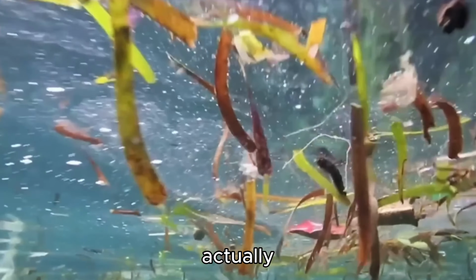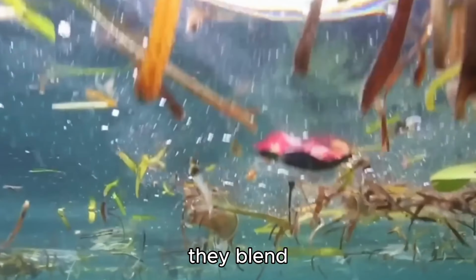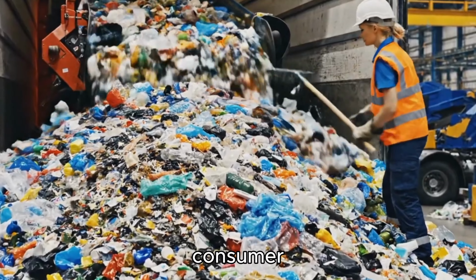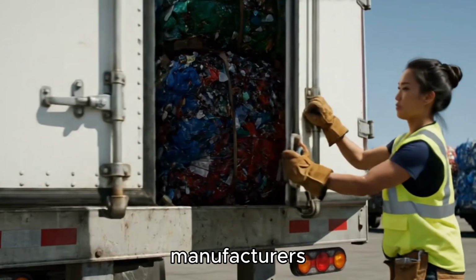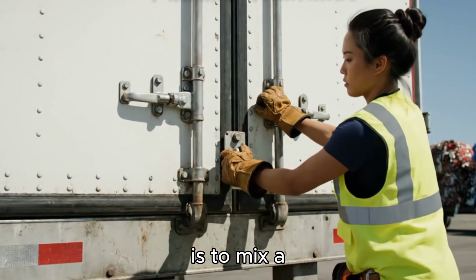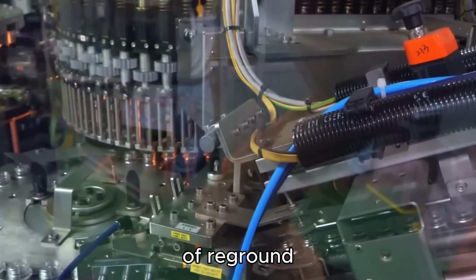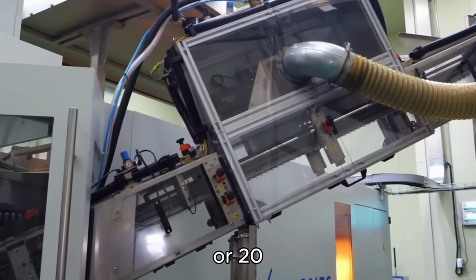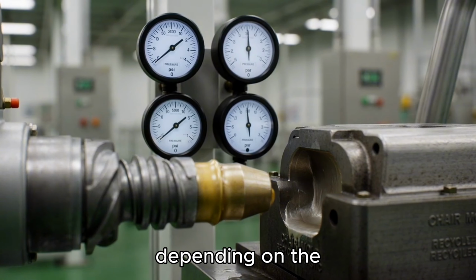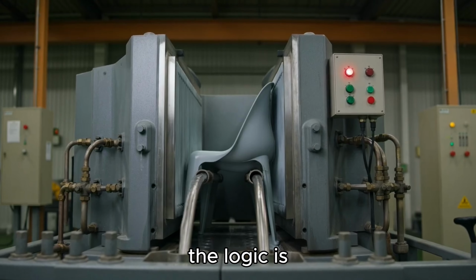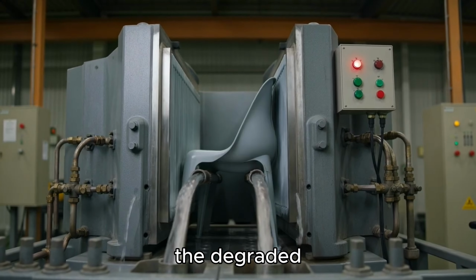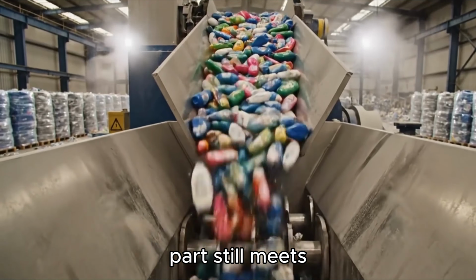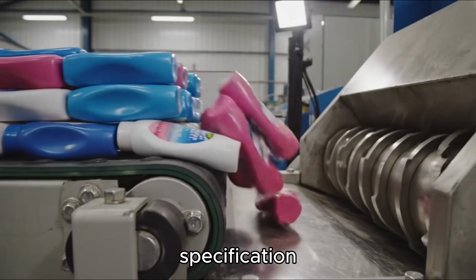So how do factories actually control this? They blend. The standard practice across automotive suppliers, consumer electronics manufacturers, and packaging producers is to mix a defined percentage of regrind back into the virgin material feed. You'll hear engineers talk about a 10% blend or 20 or sometimes 30 depending on the application. The logic is straightforward. You dilute the degraded material enough that the finished part still meets its mechanical specification.